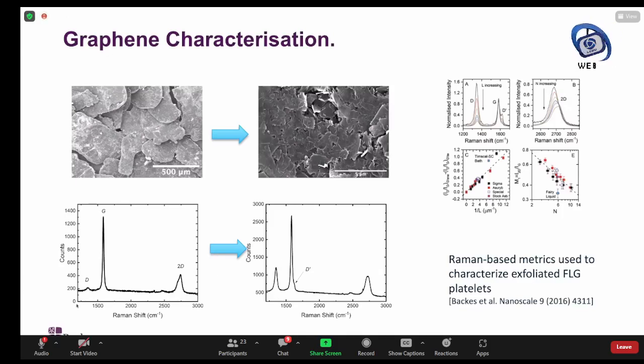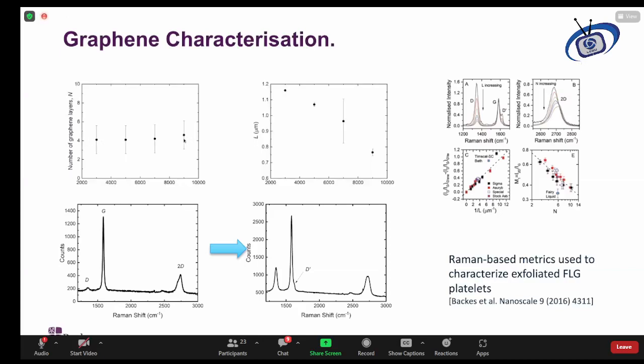There are three main peaks labeled D for defect, G for graphite, and 2D. And you can see that the shape changes and the relative intensity changes. And from that shape and intensity change, we can determine, using metrics that are available in the literature, the thickness and the linear extent. So we find that our graphene platelets are 4 layers of graphene thick on average, plus or minus a layer. And that's fairly independent of the way in which we produce them.